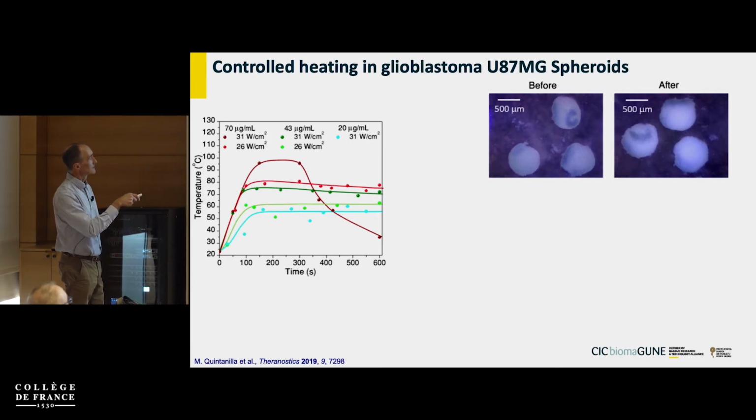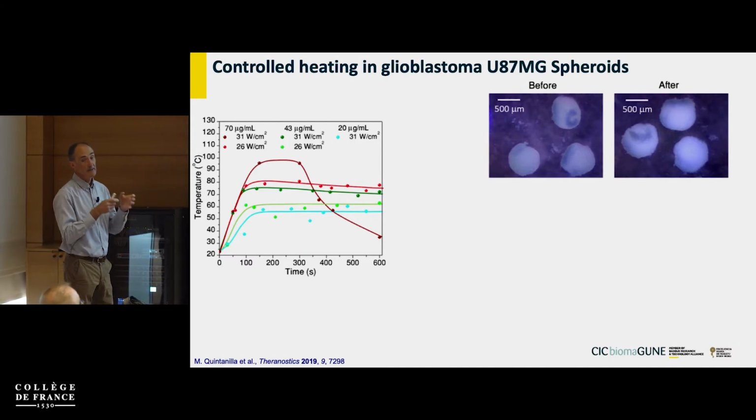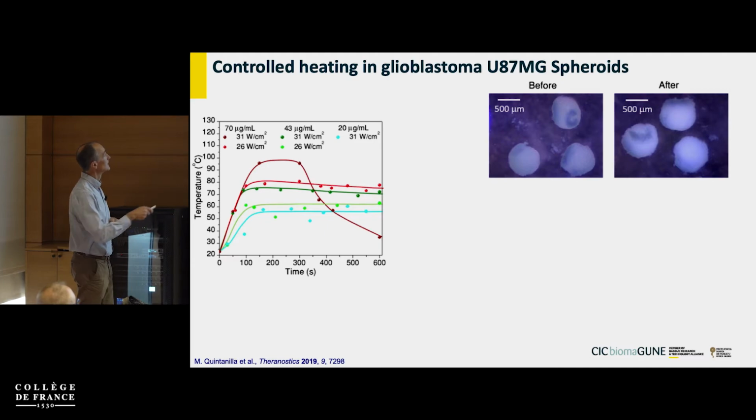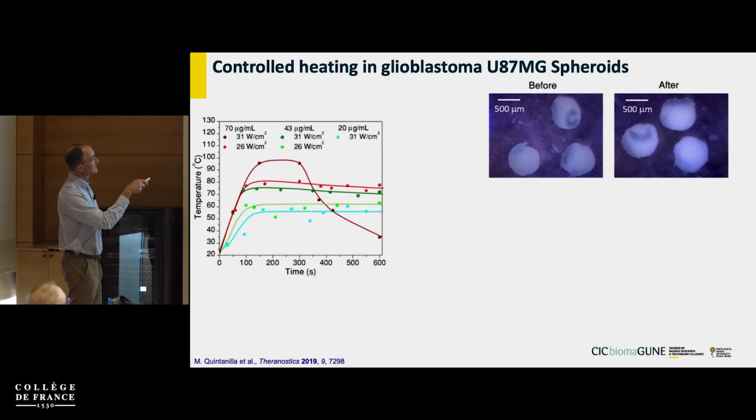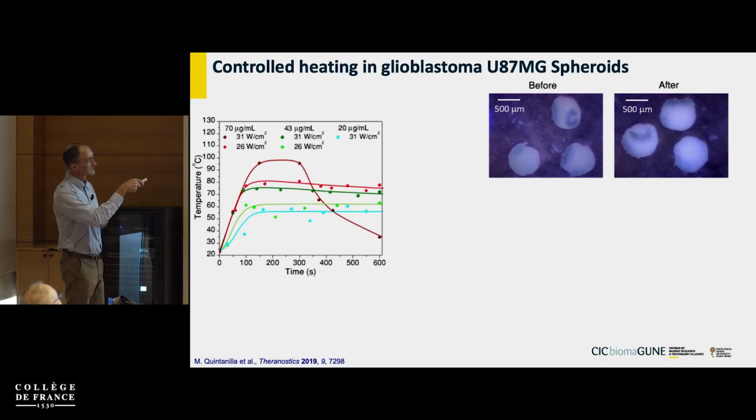Well, of course, the increased temperature as we increase the number of particles means that the laser is heating more particles, so they are releasing more heat to the system. And then at some point, there is a compensation between release of heat and dissipation through diffusion of heat. In this case, the intensity is so high and the number of particles so high that at some point we get reshaping of the particles. And so there is a decrease in the efficiency of heating.